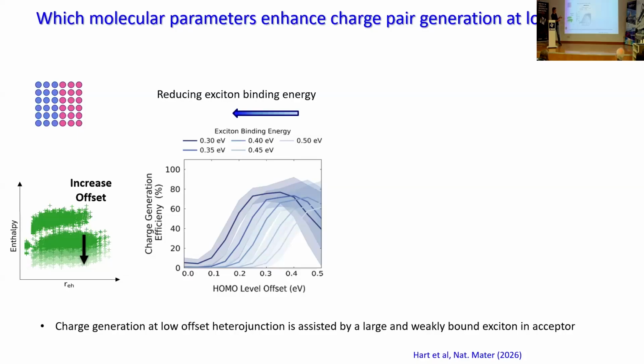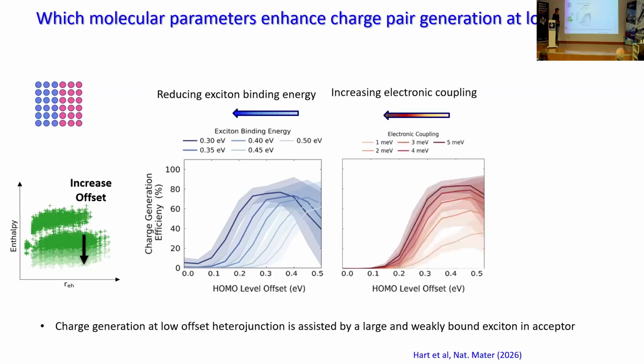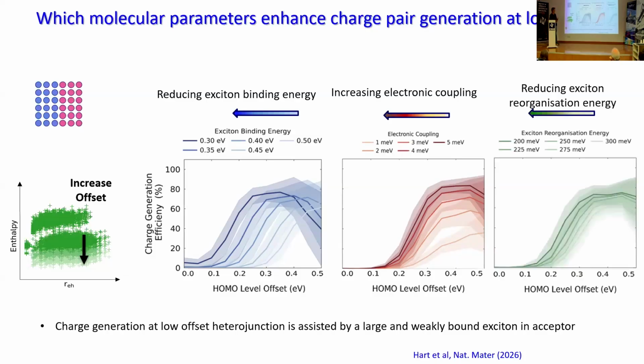And so the model is telling us that one reason, and this wouldn't surprise anybody who works with these materials, one reason would be if the exciton binding energy was smaller. And then maybe less obvious things. Another reason can be if the electronic coupling between neighboring molecules is larger. And another would be if the reorganization energy of the exciton is smaller. That would mean its lifetime would be longer.